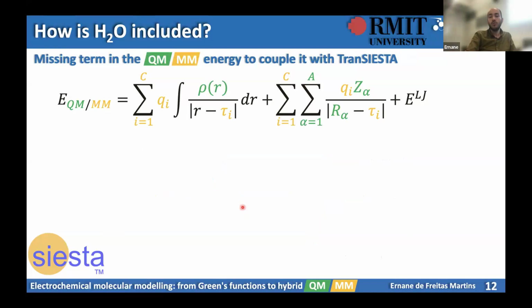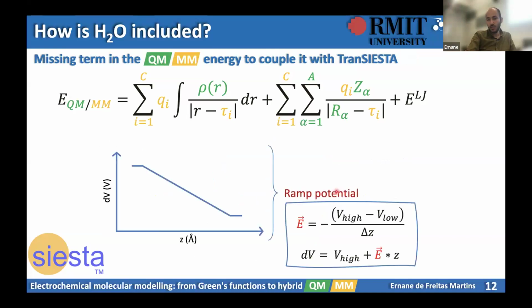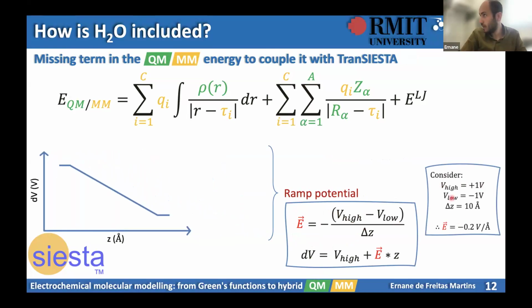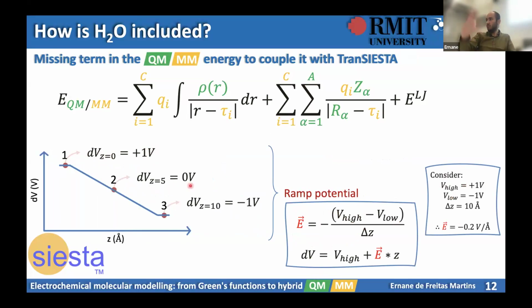So there, what we do, this ramp potential, is what we do in Transiesta. So basically, considering the high and the low voltage and the size of your simulation cell, you can compute what is the electric field generated. And then you can plot this ramp potential. If you check, considering 2 volts applied, you can see 3 regions of this ramp. So here, where Z is equal to 0, you would have plus 1 volt, at the center 0 volts, and the other side minus 1 volt. It's the same thing I showed in the other slide.